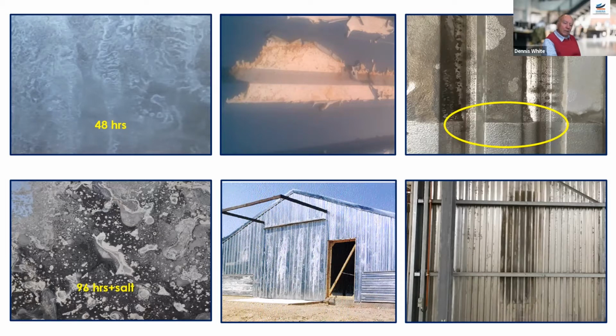The one in the top middle is an example of color-coated material that got wet and got left out in the open for an extended period. And you can see what's happened to the coatings there. One's got to remember, when you come to color-coated material, it's invariably color-coated on one side. So on the intended exterior surface, you've got your metallic coating, a transition layer, a layer of primer, and a top coat. Whereas on the reverse side, you've basically just got a 5 to 8 microns nominal coating of paint.